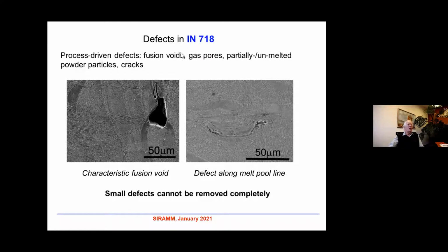The situation in Inconel 718 is shown here. Again, the situation is very similar. Here you can see a characteristic fusion void, quite large. Here on the right-hand side, you can see the defect along the melt pool line. This is a melt pool line, and the melting was not good enough. So here is a small crack. It is important to say that very small defects cannot be removed completely in the case of both materials. When they are very small, then from the point of view of fatigue, it is not decisive. When they are large, it is dangerous.